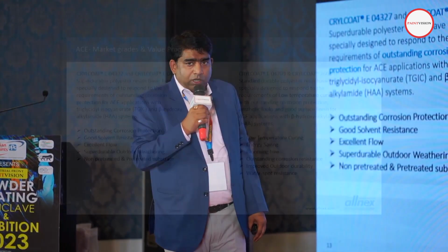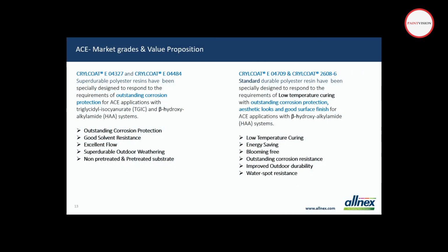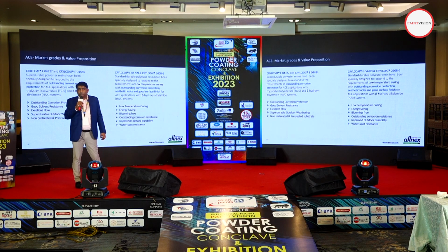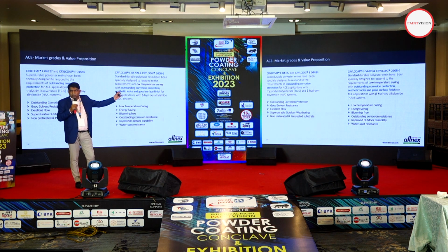These grades we can also use where we doubt that the pre-treatment is good enough. A lot of the time, the pre-treatment on the substrate is poor. Still, these grades will perform in terms of corrosion protection or corrosion resistance. It will pass the salt spray hours.